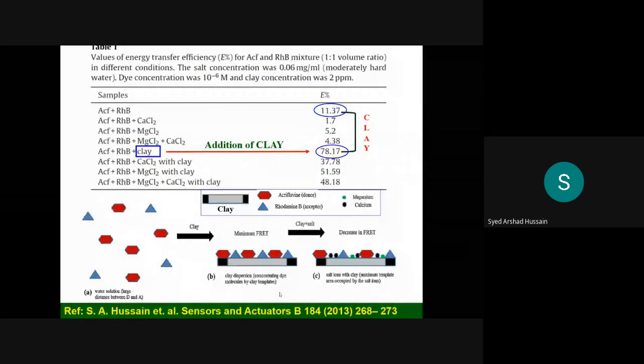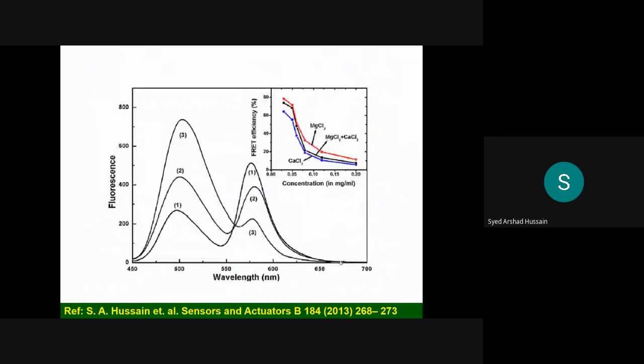And this is schematically shown. You see, in a normal system the distance is very large. So in clay, we incorporated these dyes; they are closely spaced, so efficiency increases. For sensing, what we did: first we put the clay in the ions, so the ions are already absorbed in the clay layer. Then we put this ion-absorbed clay system on the dyes. Then the dye is absorbed. But in that case, since some ions are already absorbed in between the clay, the dyes are less closely spaced compared to the earlier one. So efficiency decreases. Based on this decrease, one can have an idea, one can calibrate.